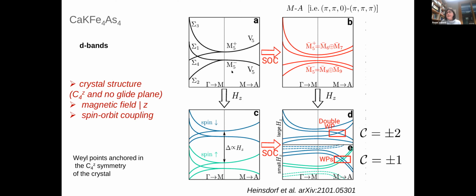So what we have, if we consider the fact that I have a glide plane symmetry broken, that I have a C4z symmetry, and I have an inversion center at the calcium or potassium, what we will expect is to have nodal lines along MA, which are fourfold degenerate: twofold because of the C4z symmetry and twofold because of the Kramers degeneracy. And I have two sets of them because calcium, potassium, iron 4, arsenic 4 has 2 iron layers per unit cell.